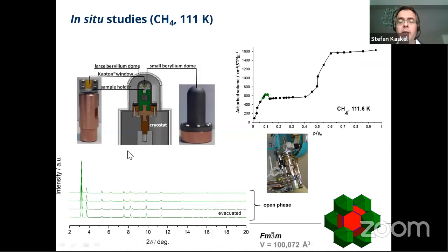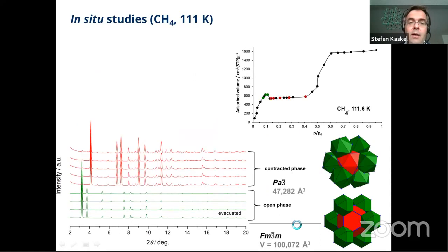So as we have this enabling technique, the in situ X-ray diffraction, we followed this kink basically with our isotherm measurements. And initially we have a huge unit cell with 100,000 cubic angstrom and a huge pore volume. And what we found is that after this step, there's a significant transformation. So all the peaks are moving to higher angles, meaning that there's a contraction, and the cell volume of the unit cell is contracting by more than 50%.